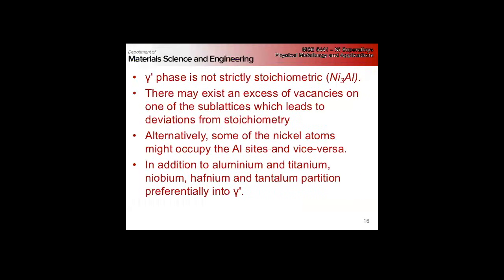The other thing we have to keep in mind is our gamma prime phase is not strictly stoichiometric. We can substitute titanium out for the aluminum, we can potentially have an excess of vacancies on one sublattice versus the other, and we can have site mismatches, nickel on an aluminum site. We also have other elements - niobium, hafnium, tantalum - which are all gamma prime formers and will partition preferentially into gamma prime.